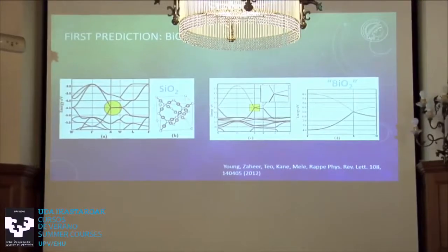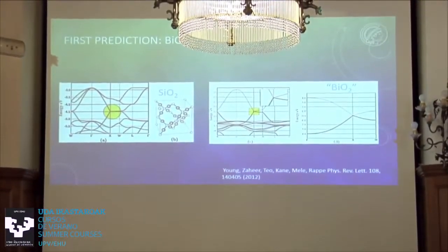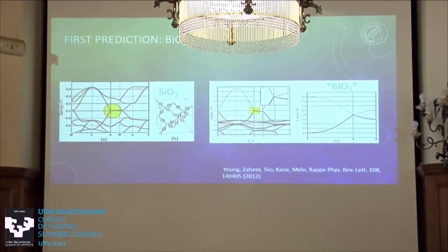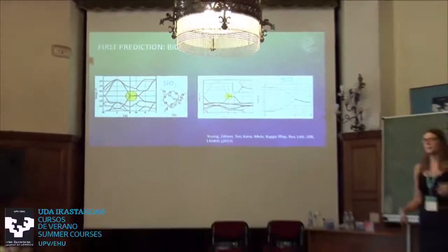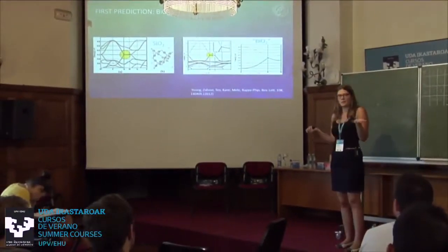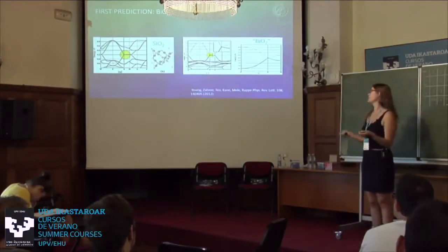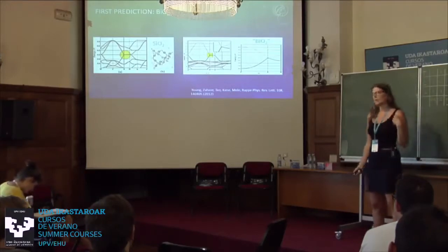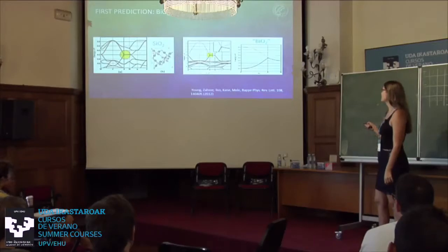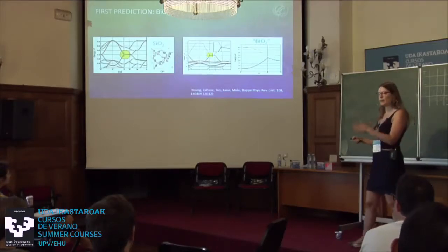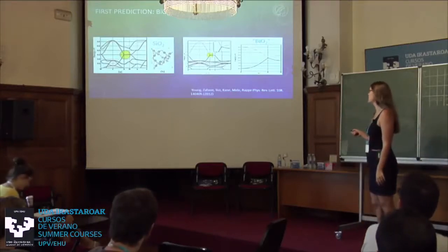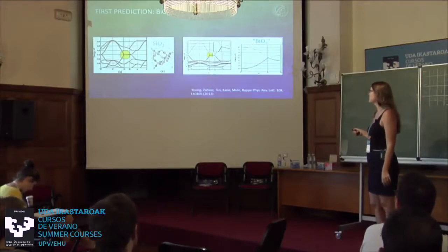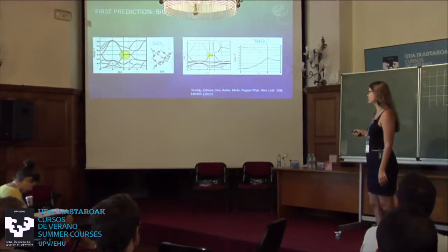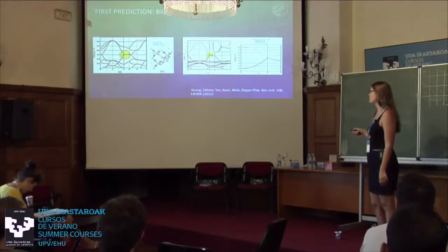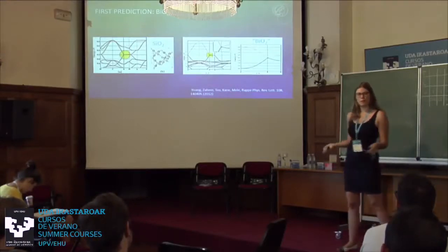So the idea was, okay, we have silicon dioxide, which is a non-symmorphic crystal. So you see the crystal structure here. And this is quartz glass. And it has, like you expect, this degeneracy at the X point. Okay, but if you look at the energy scale, it is at minus 4.5 eV. And this makes sense because quartz, you might know it from glasses or anything you have, is a transparent insulator. It has a huge band gap. So the feature we care about is down here, 4.5 eV below the Fermi level. And then the idea in the paper was, okay, if you put bismuth here instead of silicon, we add an electron, bismuth being one to the right of silicon, and therefore we shift the Fermi level to the place we want it, and now we have the crossing exactly at the Fermi level. And also they use bismuth, which is much heavier than silicon, to lift those two bands here, close to degeneracy, a little bit further away, so this is a cleaner Dirac cone.